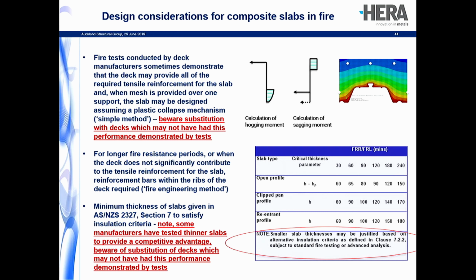The other thing to watch also is, again, to try and get some competitive advantage. Most manufacturers try and do the tests at the thinnest slab possible, and often they go to smaller slab depths than is recommended in AS/NZS 2327, which is shown here in this table. And again, it's to give them a bit more of a competitive advantage against other manufacturers. So one thing to watch is be very careful if there's any substitution on any of your jobs.